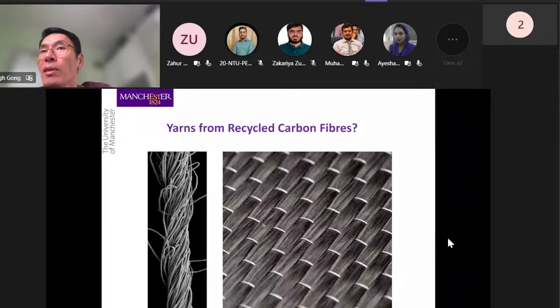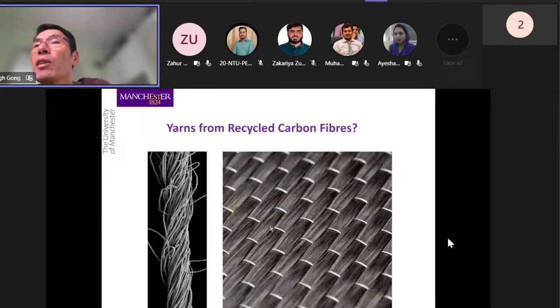However, if you produce twisted yarns, the characteristic of the yarn and the resulting composite will differ from filaments, because the yarns will have better stretch, and by using different levels of twist, you can also control the amount of stretch.